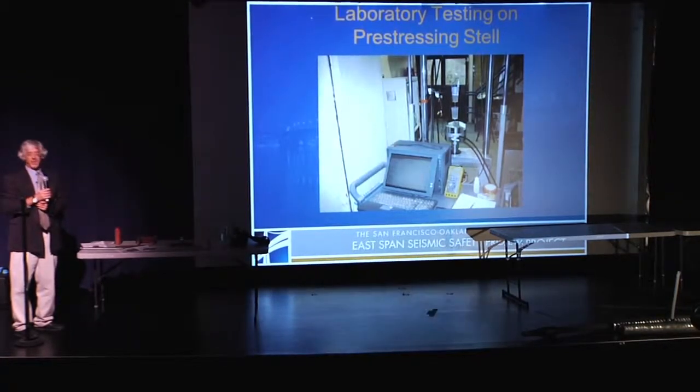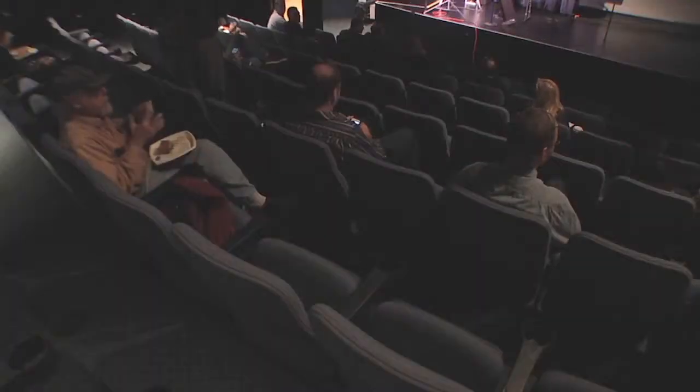And at the end, we had statistical information, strong engineering information, that something like 1.5% of the strands had what we termed moderate corrosion. That means we were losing about 5%, something like that, of their strength. What's the right balance?